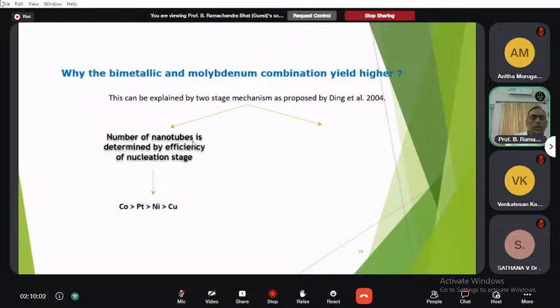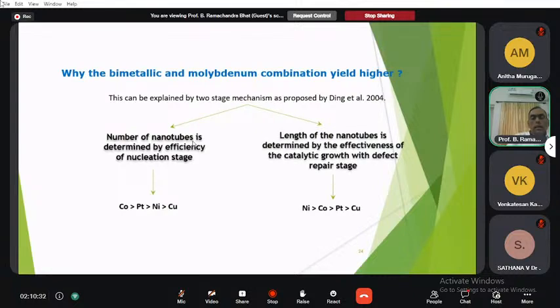So here it says that the number of nanotubes is determined by the efficiency of the nucleation stage. This nucleation stage is the first stage where the nanotubes are formed, and it is favored by cobalt at a higher rate compared to platinum. Platinum is greater than nickel, nickel greater than copper. So cobalt takes the upper hand in this case. And then the length of the nanotube is determined by the effectiveness of the catalytic growth with the defect-free or defect repair stage. So for the length of the nanotube, a combination of cobalt and nickel is chosen, so that we get a better, defect-free nanotube.